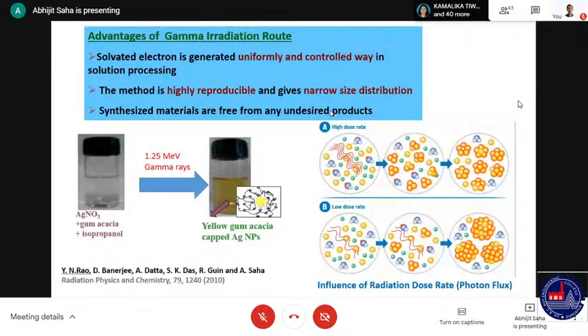Otherwise, what you normally do is use lithium aluminum hydride, sodium borohydride and so on. And that remains in the medium, and that complicates the further processing. So this process is considered one of the cleanest methods for synthesizing materials. For example, silver nitrate is initially colorless and it becomes colored.